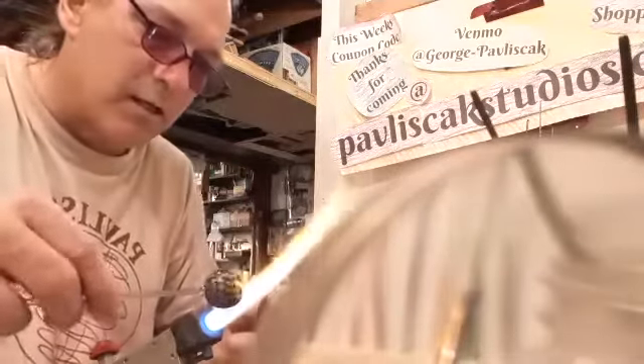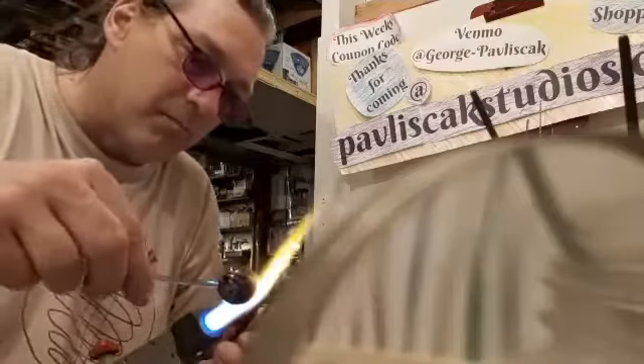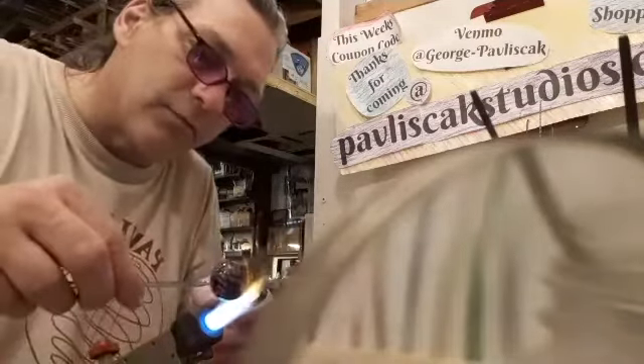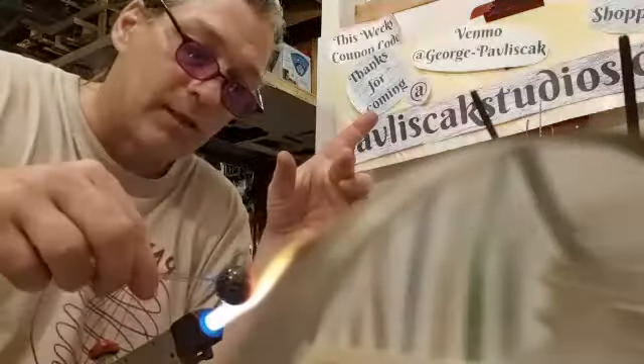Usually I don't like to put older glass into a marble just because I'm devoting so much time to making a marble. I want to make sure that I'm using all the materials with the same density and coefficient of expansion and contraction. And that can change as the fluxing agents in the glass that give it its workability vaporize out. When you first get glass to work, they say it's long because it's got a lot of chemicals in it that let the temperature range of its workability be wide. As those fluxing agents work out, your glass gets shorter, which means the temperature range of its workability is getting narrower and narrower. So if you have glass that's narrow and glass that's long, even of the same brand, that could be a difference in the coefficient of expansion and contraction and cause annealing and cracking problems.